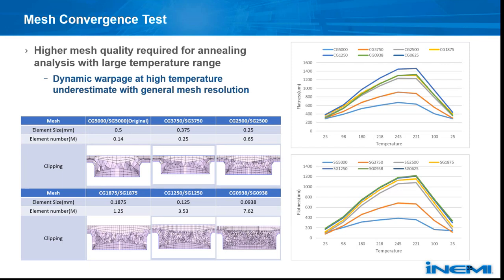So we did a mesh convergence test by decreasing the element size and increasing the total number of elements. The mesh resolution is shown in the left chart, and the results from the convergence test are shown in the right side plots. The upper plot is the dynamic warpage of the center gate model, and the lower one is the side gate model. We can see the flatness increases significantly when we decrease the mesh size, and it converges to a value very close to the experimental result.